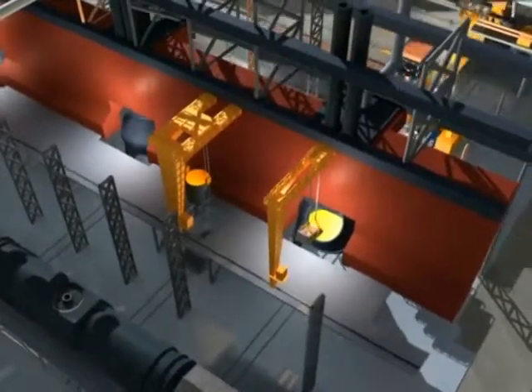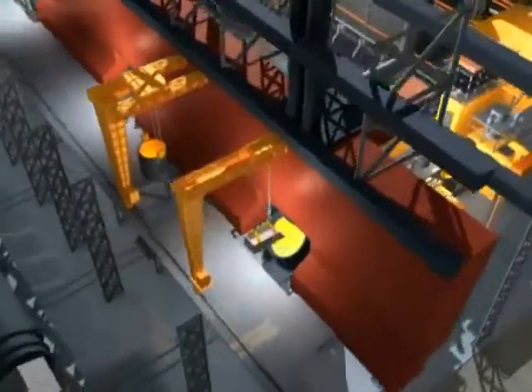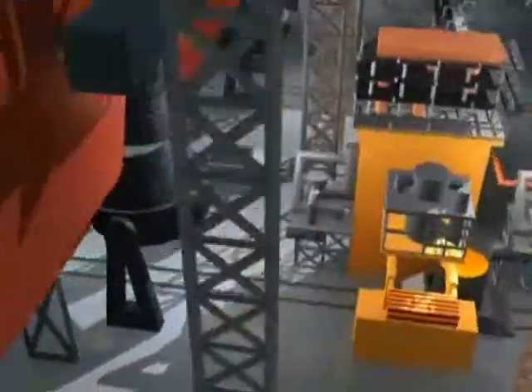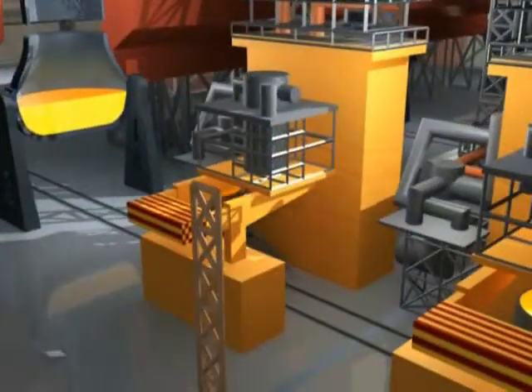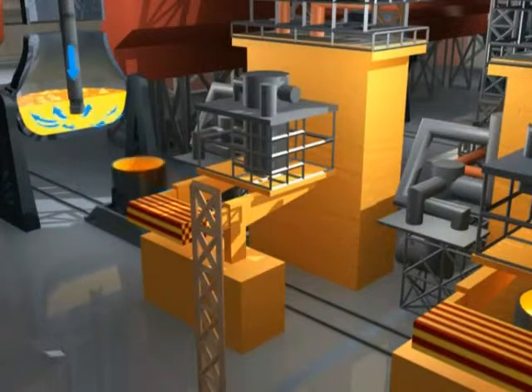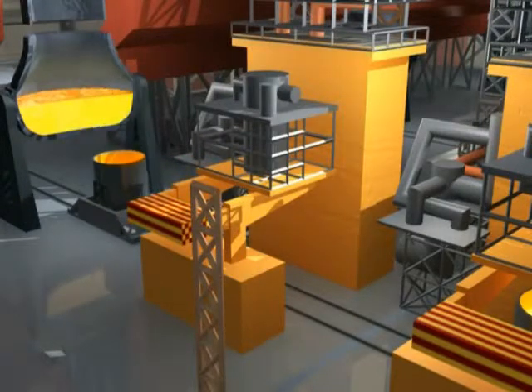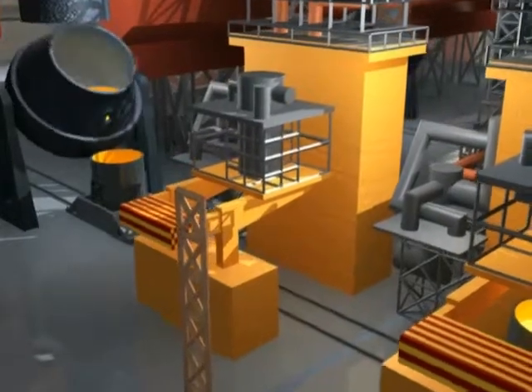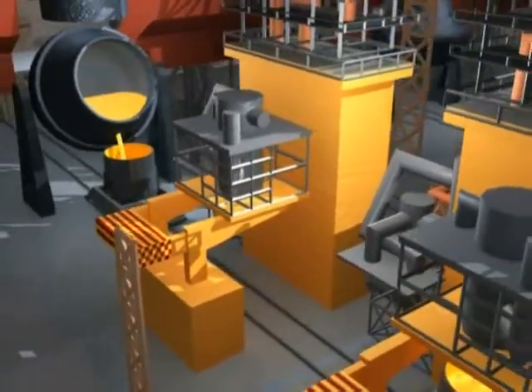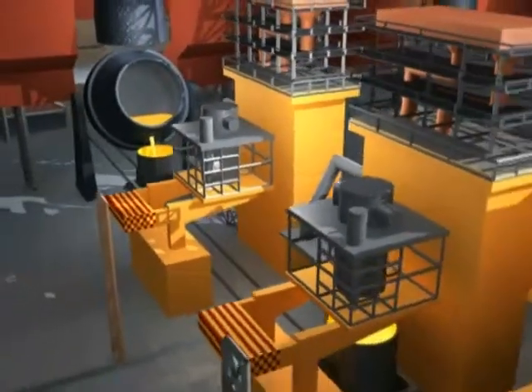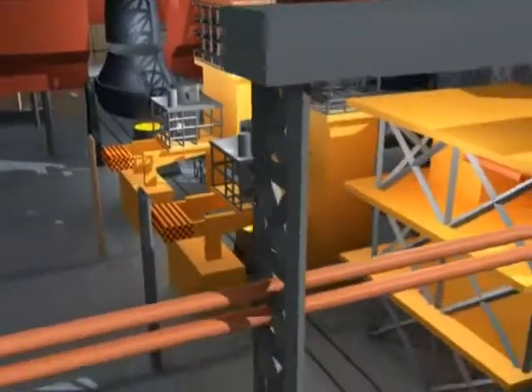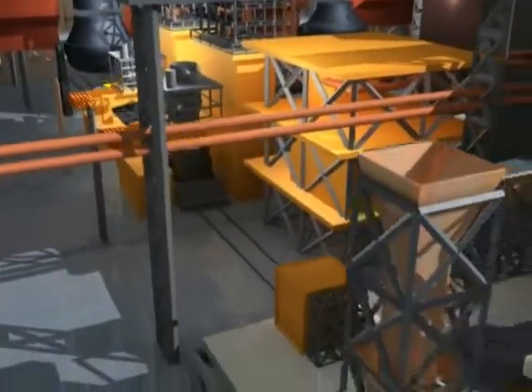Scrap is added to the hot metal at this stage. Then oxygen is blown into the converter, oxidizing the carbon and silicon contained in the hot metal. During the smelting process, impurities containing sulfur and phosphorus are removed from the charge. The end product of the process is unrefined steel, ready for subsequent treatment in steel refining or secondary treatment units.